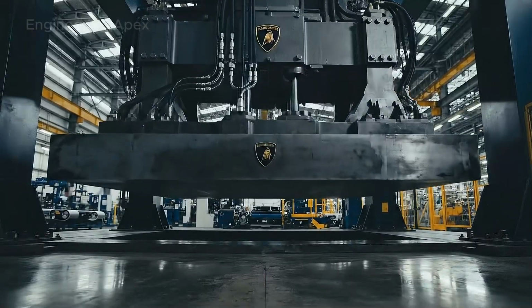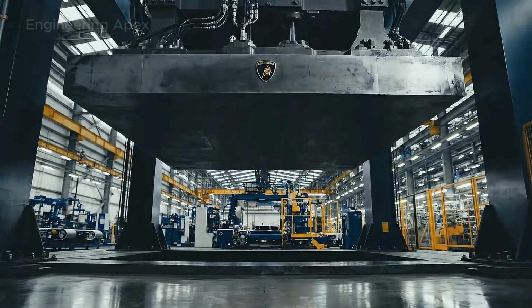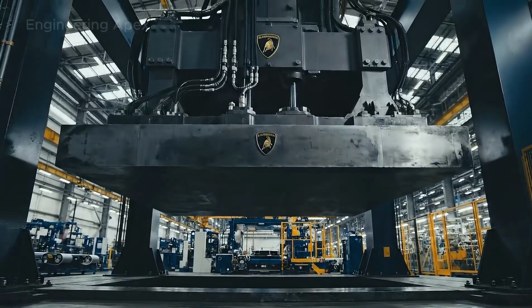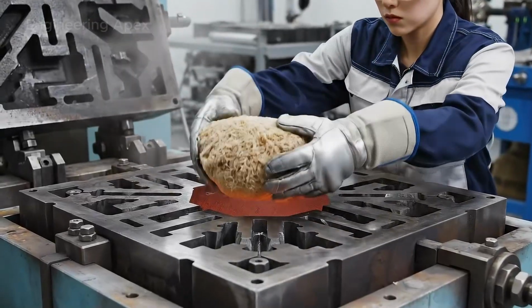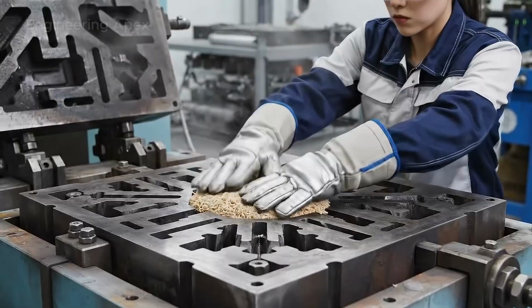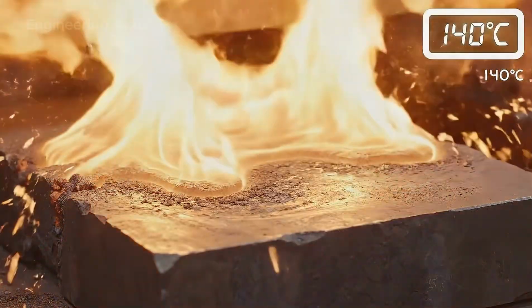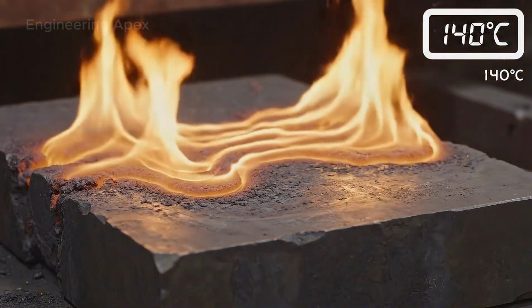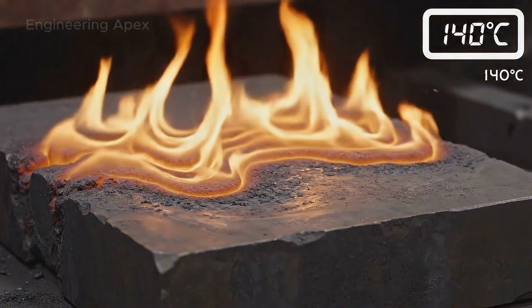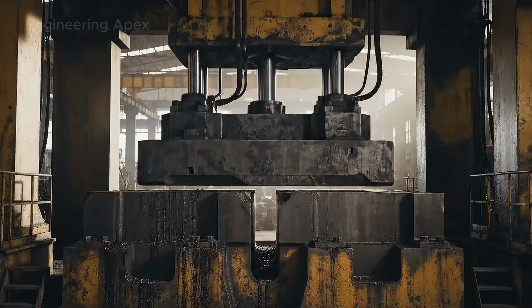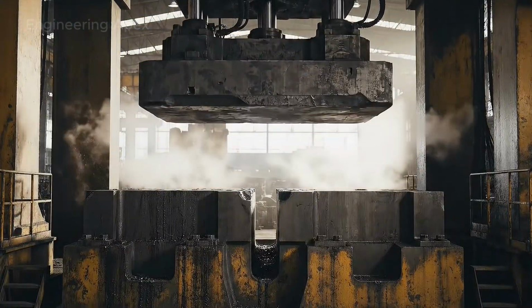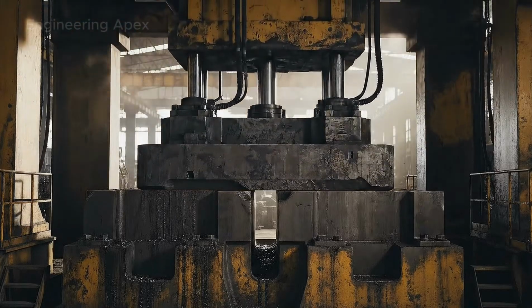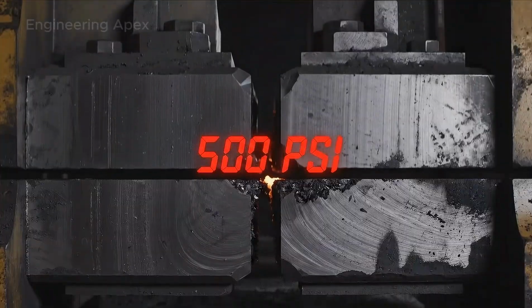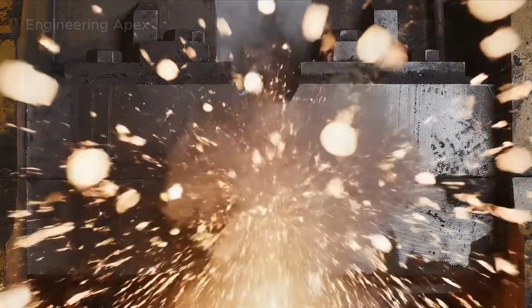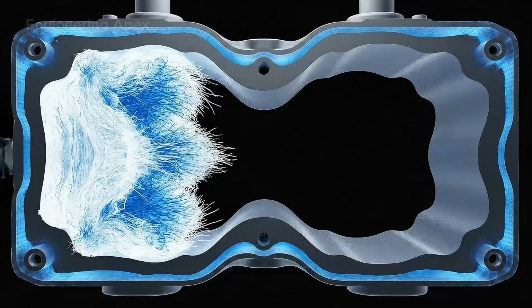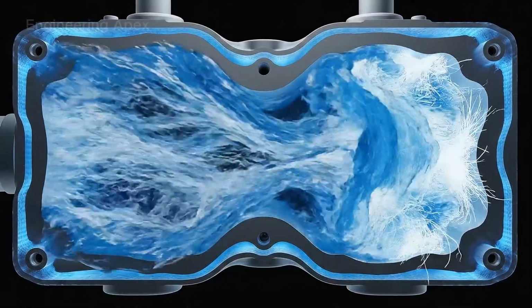The manufacturing process itself is a study in violent compression. The pre-measured charge of chopped fiber and resin is placed into a heavy-duty steel mold. Unlike the autoclave method, which gently coaxes the resin to cure using vacuum pressure and moderate heat over several hours, this process is aggressive. The mold, heated to precise activation temperatures, closes under the immense force of a hydraulic press, often exerting over 1,000 psi upon the material. This leads to a critical phase change.